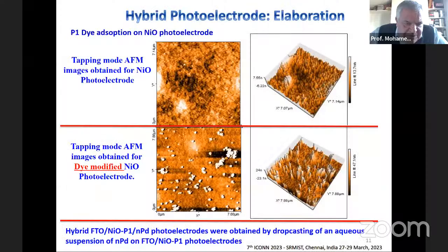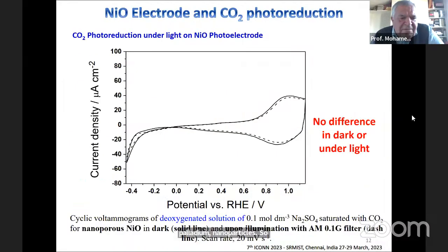Nickel oxide photoelectrode, the dye-modified nickel photoelectrode, and finally the hybrid photoelectrode, which is composed of the dye-modified nickel photoelectrode absorbing nickel palladium nanoparticles. So the final electrode was the hybrid one. So we checked the activity against CO2 photoreduction of all these electrodes.